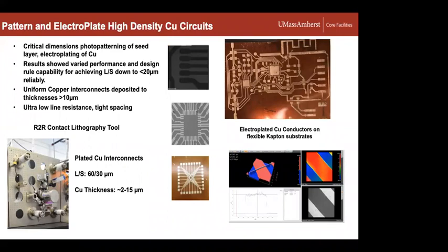And what we've been able to achieve, if we look at the right, is pretty good patterns. I mean, the pattern limitation here is dictated by the photoresist pattern, which technically you can get down to 10 microns or better. It's submicron for silicon photolith patterning, but in this case, the resolution is limited by a flexible plastic mask that can be created. And those are typically on the order of 10 to 20 microns. In many cases, they're going to tell you 50 microns is a design rule limit, but we've seen a little bit better than that. And when we electroplate, it just follows whatever pattern you created in a resist. We get very nice, crisp patterns. In this case, we have, I think, line and spacing on the order of 60 microns line width, 30 micron spacings.